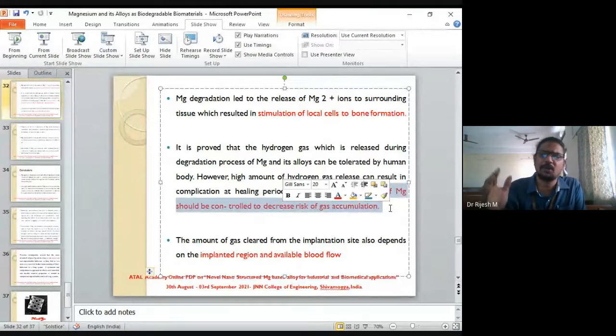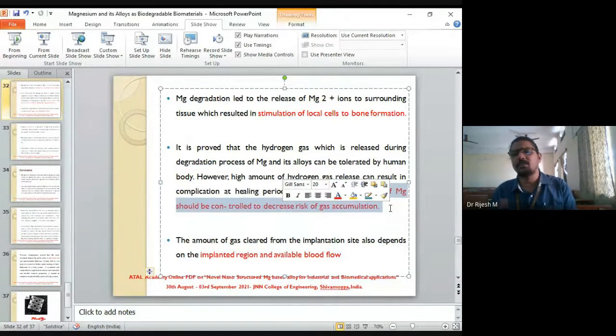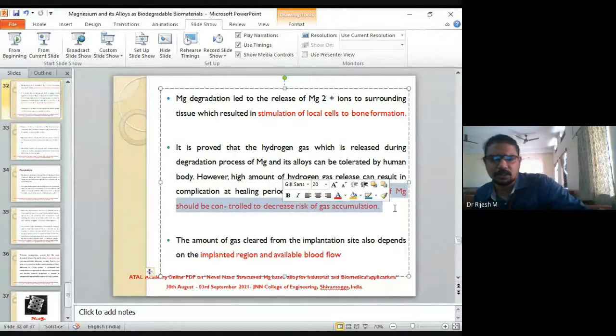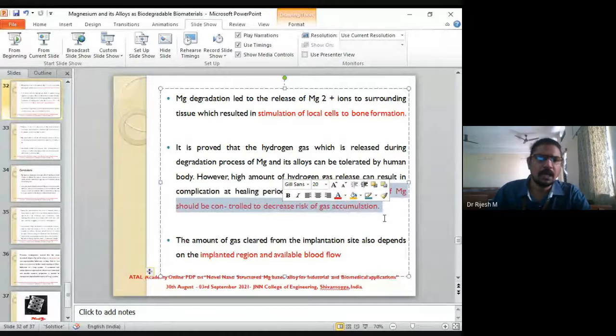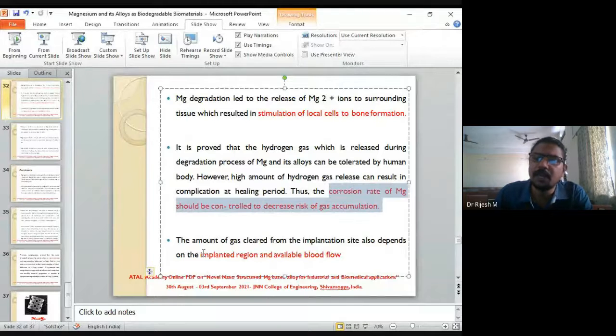Controlling the corrosion rate of magnesium alloy starts with a lot of things. What are the alloying additions that you're adding? What is the manufacturing route? Are you going for a porous material? If so, do you have interconnecting pores? What is the surface roughness of your material? All these things are important in deciding the corrosion rate. The amount of gases cleared from the implantation site also depends upon the implanted region and the available blood flow. Which region it has been implanted in and the available blood flow in that region decides the amount of gases cleared.